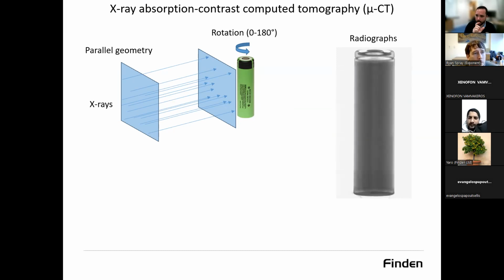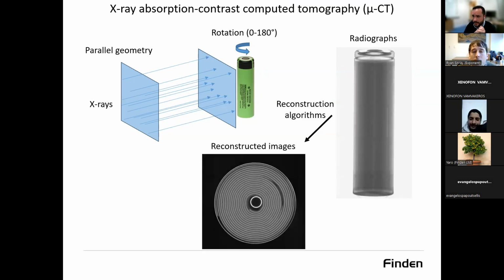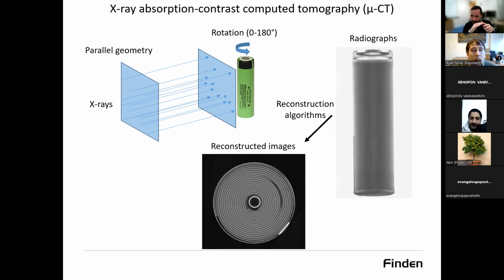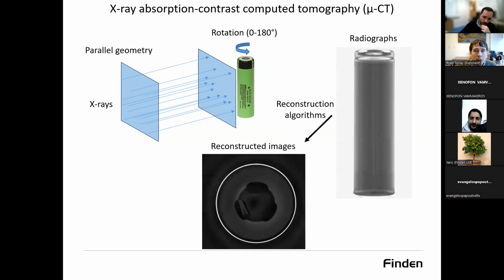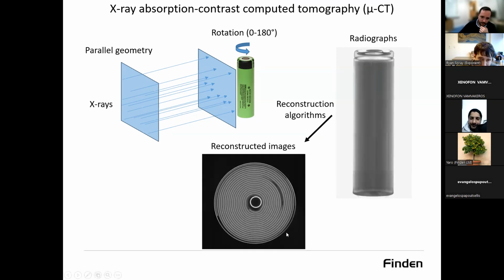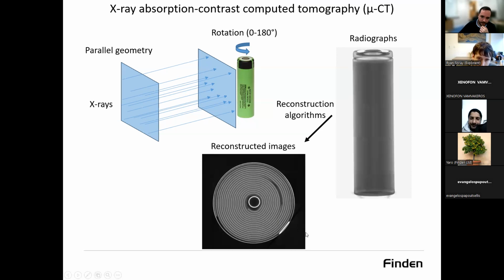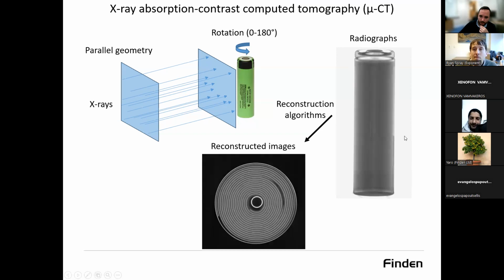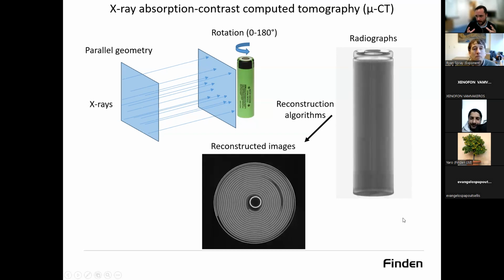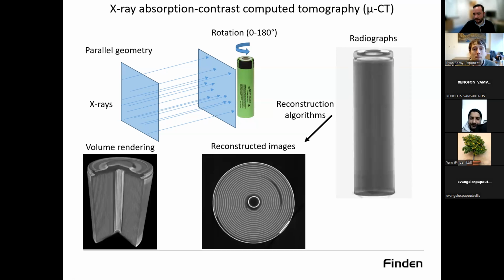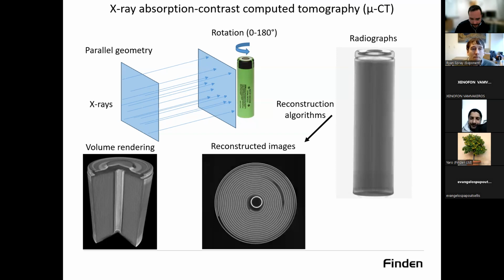But at the same time, we are rotating our sample. So you can see here the radiographs that we're collecting while the sample is being rotated, covering 0 to 180 degrees angular range. We can then use various reconstruction algorithms and get back our images. These are images that correspond to 2D cross-sections of our sample. So you can see probably here, just a second, a bright part will appear. This is the tab that you can see here on the battery, right? And of course, if you have a 3D matrix, you can also start having 3D volumes, 3D volume rendering, etc.